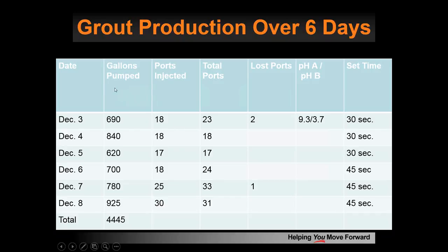And then just to give you a little flavor, we did this work December 3rd through the 8th, so it's about 6 days. We were pumping about 700 gallons per day. This tells you how many ports. And we lost actually 2 ports, so we couldn't get them out of the cores, but all the rest of them we got out in renews. We had pHs. Our A side was about 9. Our B side was 3.7. And then our set times were about 30 seconds to 45 seconds.